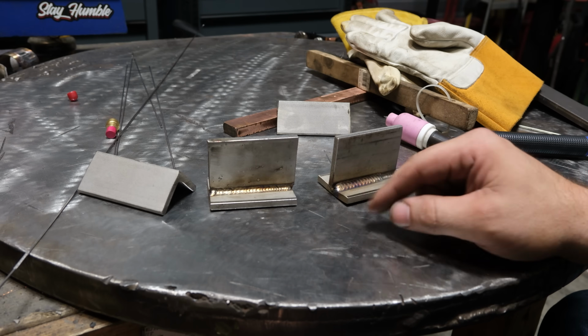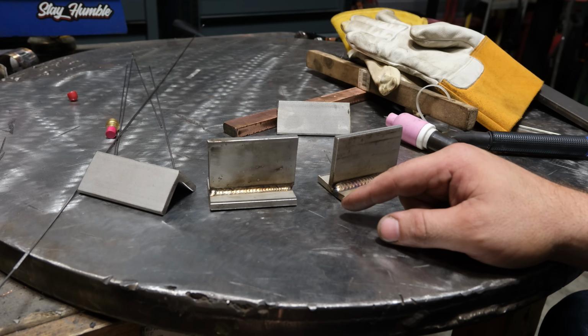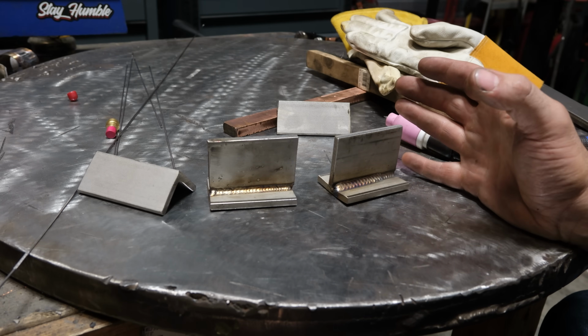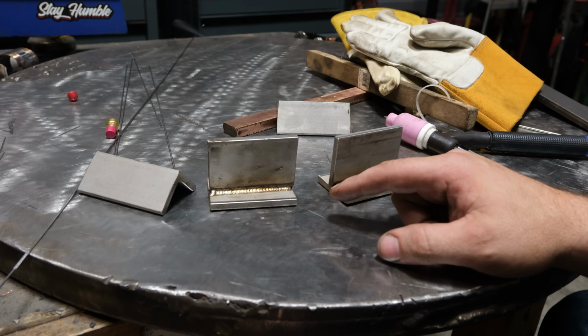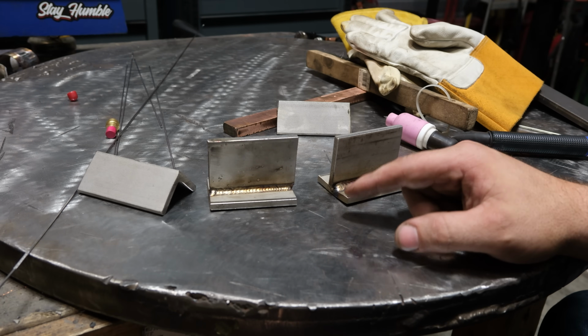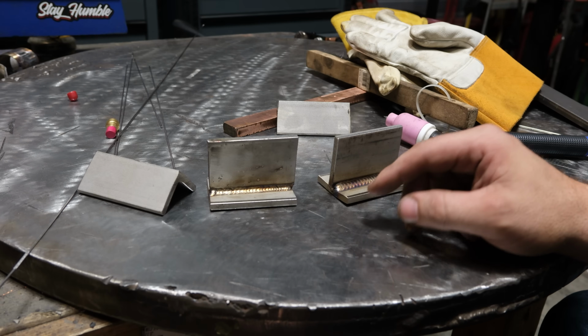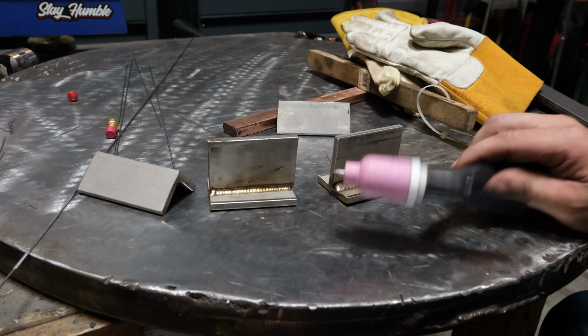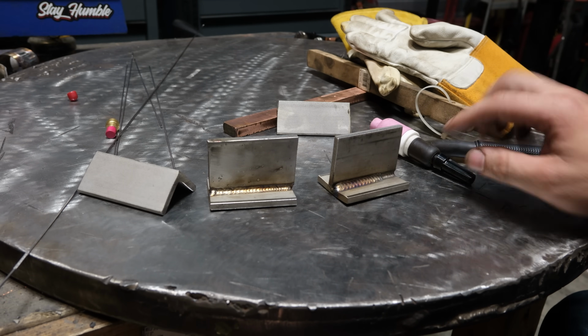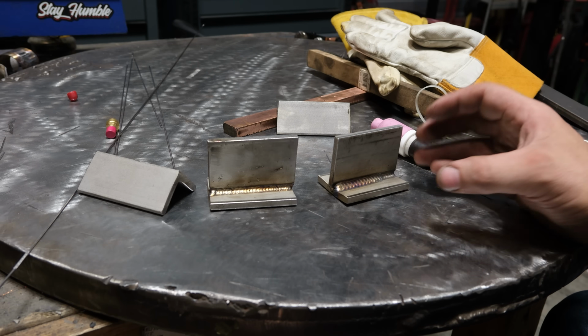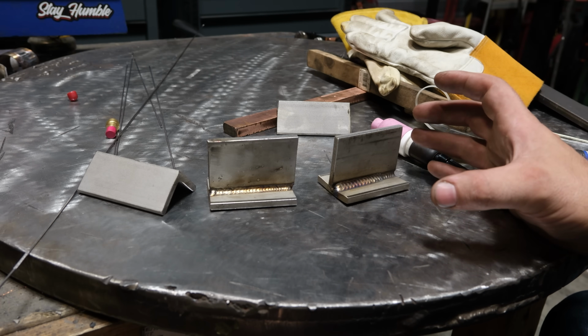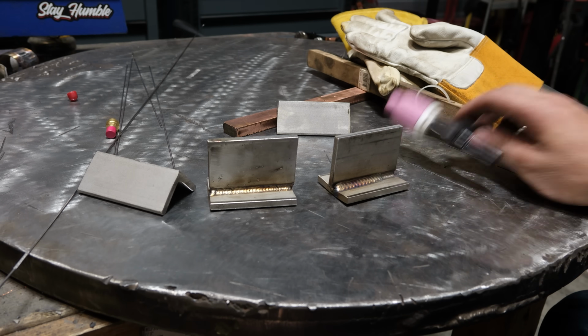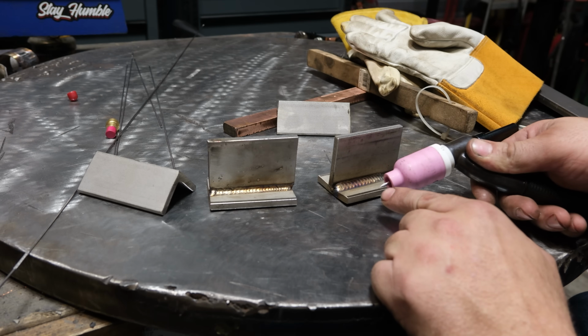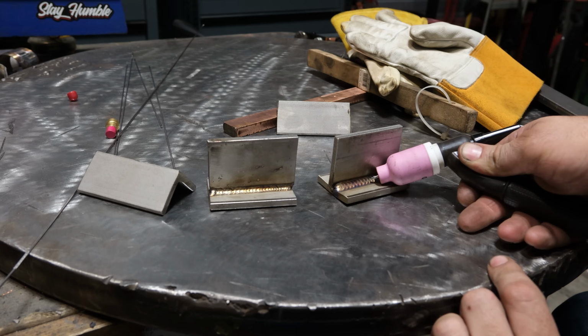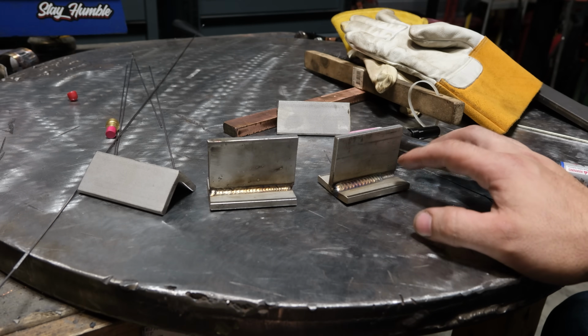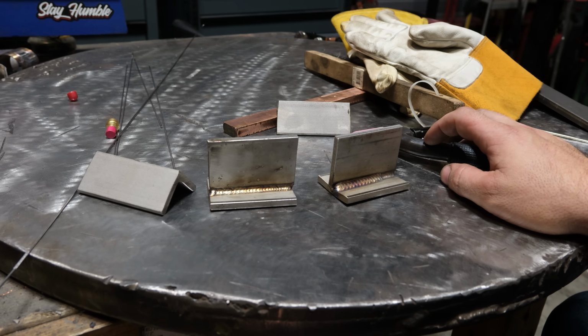Anyways, even though I ran 140 amps on this, you can see the color is what you would expect out of a very clean TIG weld, which is basically a light straw to pure silver. And 100% that's due to 2 reasons. One, despite running a number 8 cup, the fact that the argon's heavier than air and it's more or less trapped in here means that you have a really good argon shielding, therefore it doesn't react with oxygen. I also had a little bit longer of a stick out here, which if you can see where the tungsten and the arc would be, you're actually covering quite a bit of area with argon shielding